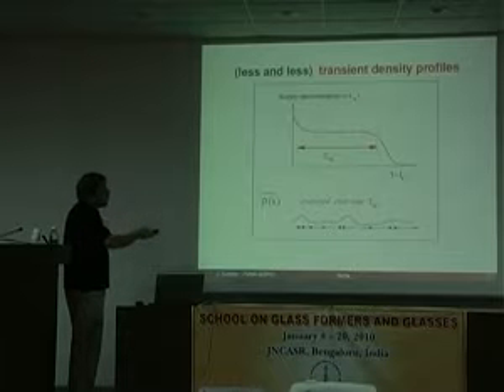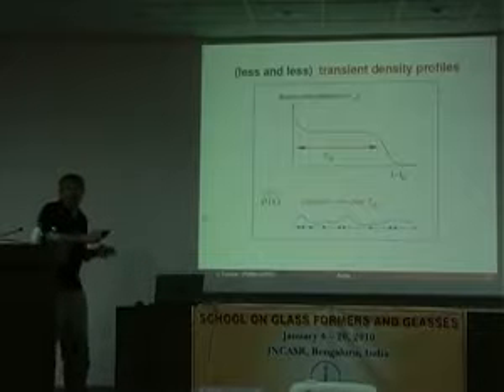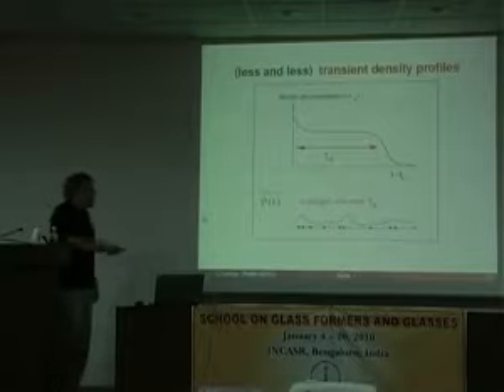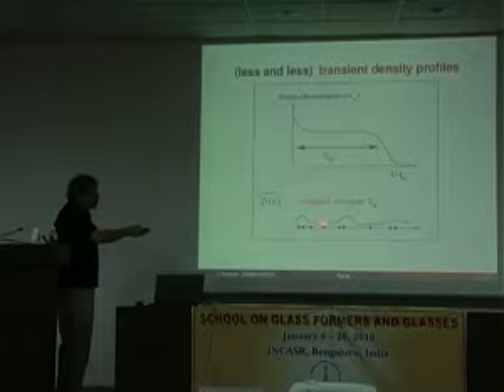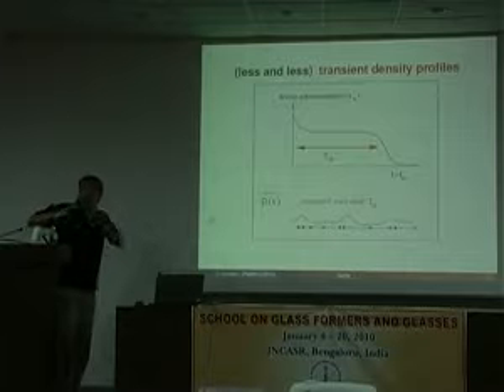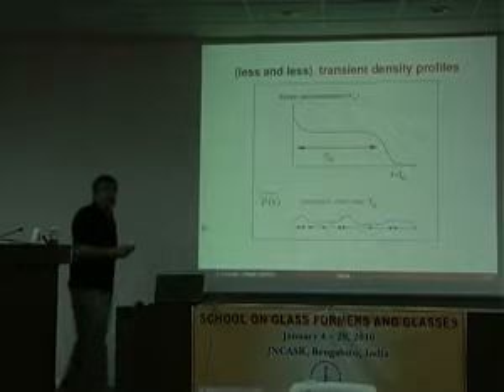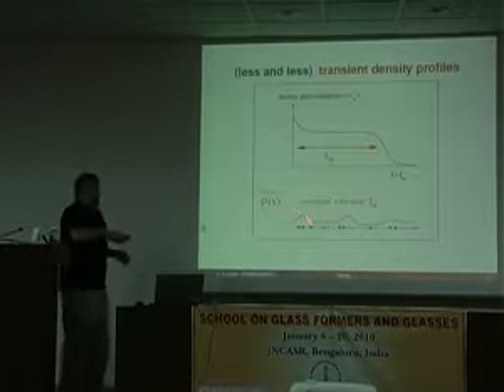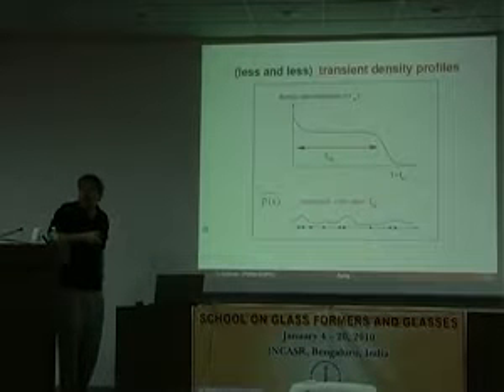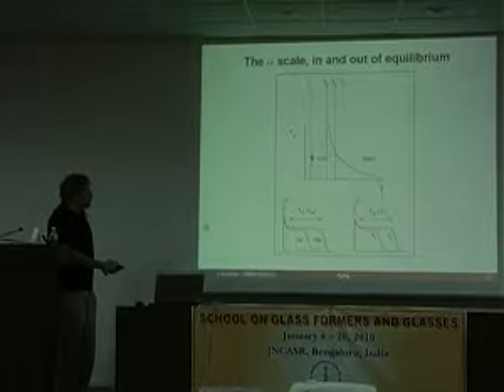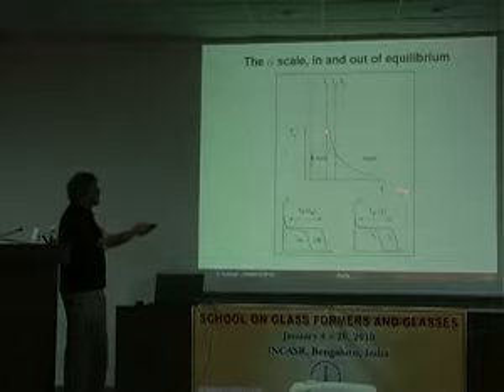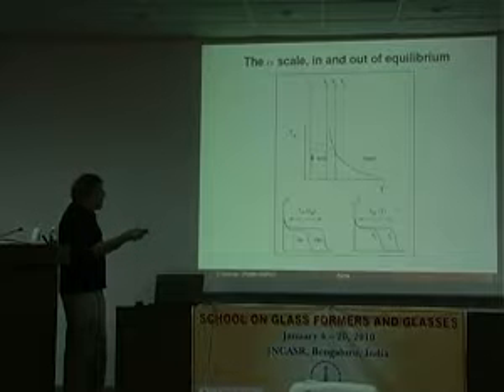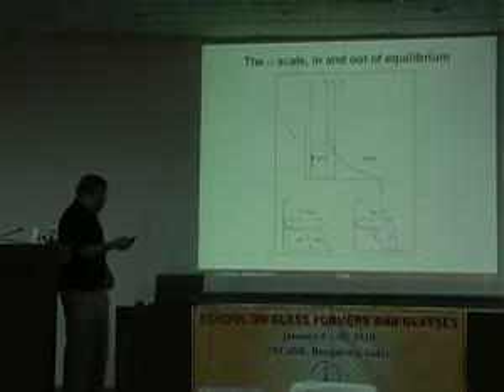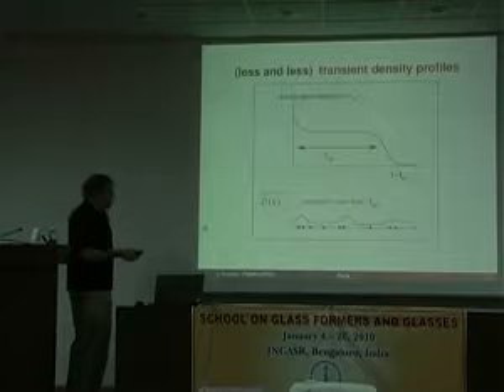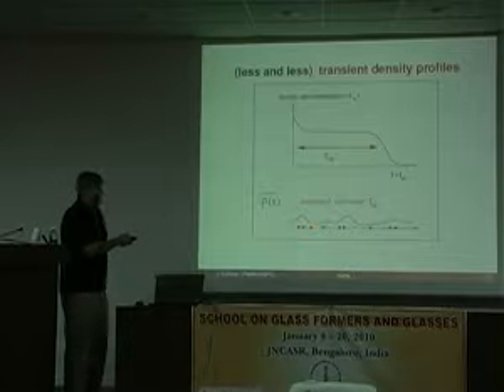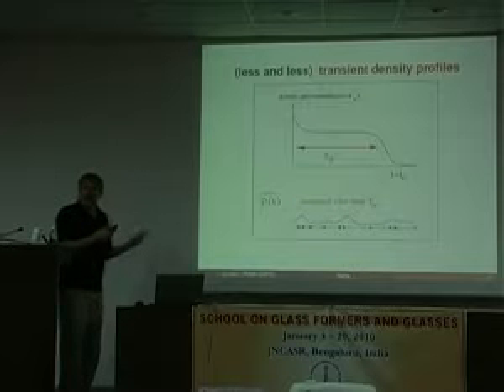Then for a long expanse of time, you can consider you have an average profile that has some shape, which is amorphous. And then at a longer time, this profile evolves very slowly, at a completely different time scale, into something else. This would be the analog of the periodic modulations in a crystal. So as you are aging, you're taking your thing here. While you are in equilibrium in a liquid, the profiles evolve, but there isn't a waiting time notion.